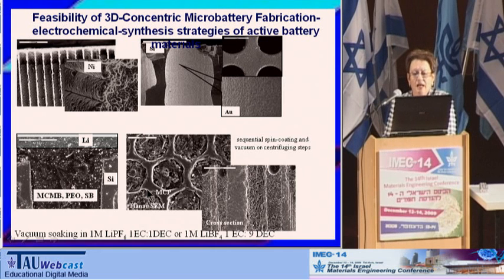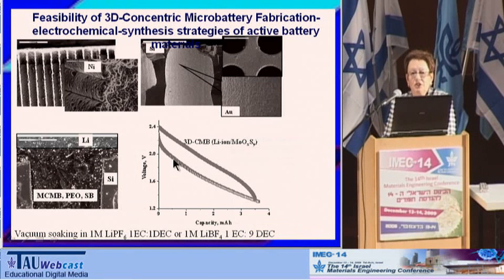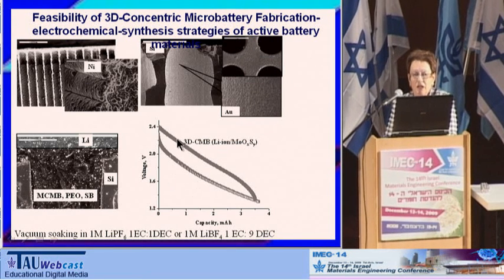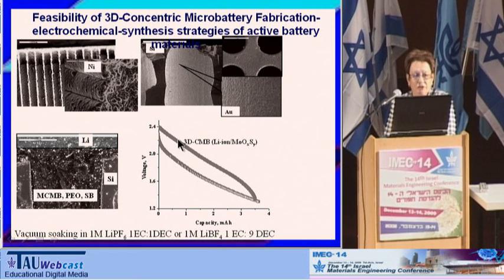With the membrane, the sequential spin coating and vacuum steps, or sometimes centrifuging methods, were used to fill in the lithiated graphite-based anode material in the remaining cavity of the microchannel. And here you can see the upper SEM view of the polished structure. The full semi-three-dimensional concentric microbattery showed stable electrochemical behavior and low degradation rate. However, the sloping character of the charge-discharge curves is disadvantageous for some applications.